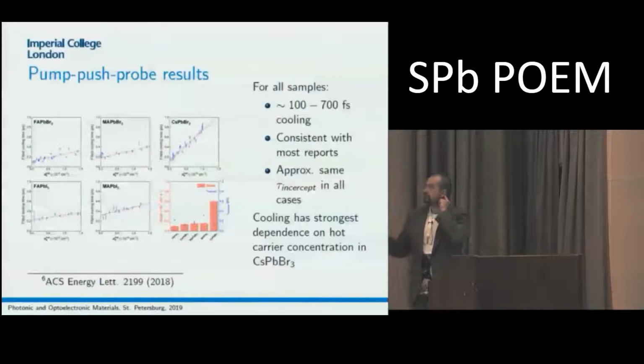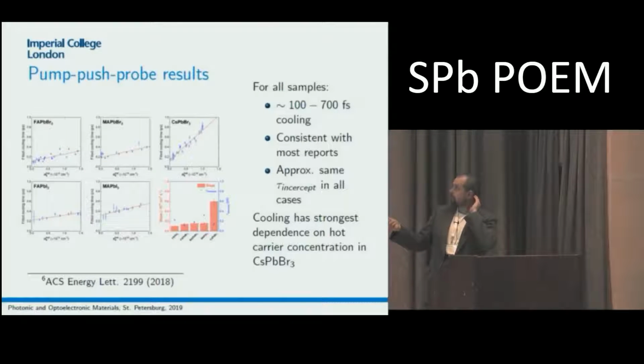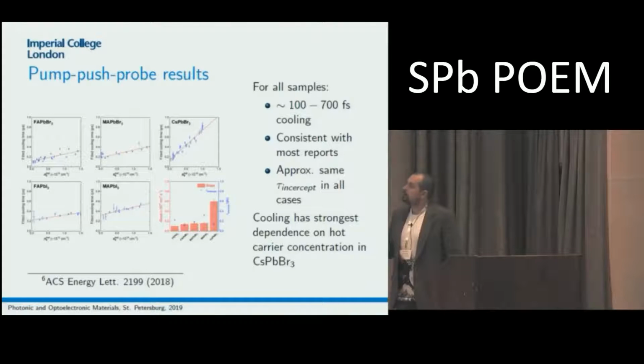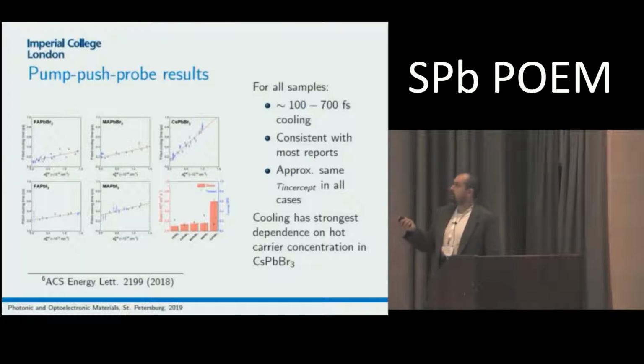and looked at different materials like lead bromides, iodides, and different acceptors. All of them have this trend of cooling time elongation, but the inorganic cesium lead bromide has the highest rate of cooling time elongation with push intensity. So if we plot the slope and the intercept time, these will be the dependencies, and cesium has a significantly stronger dependence on hot carrier concentration.